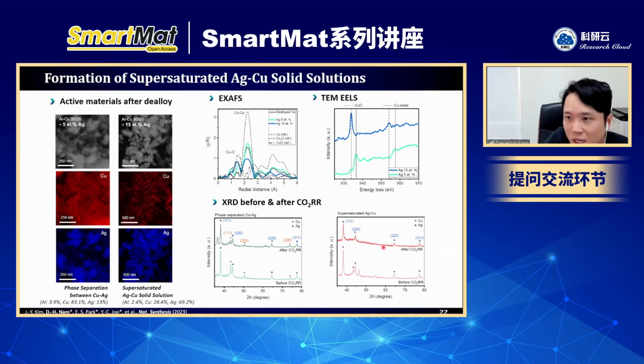before and after. But what I want to say is that although they change during the CO2RR, the phase separated one maintains its original structure and its interface changes only slightly. In the same way, the supersaturated one has a slight change in surface structure. But when you compare the after-CO2R states, they still maintain the difference between the supersaturated one and the phase separated one.